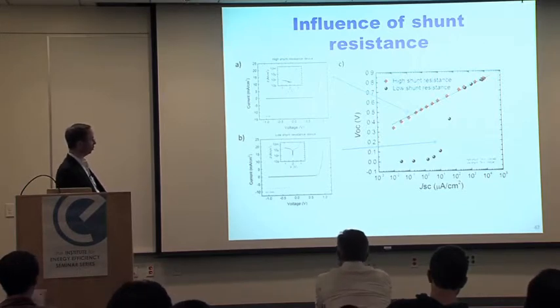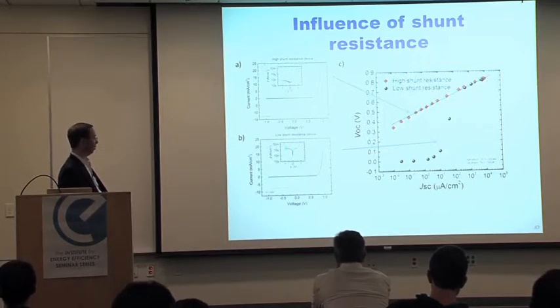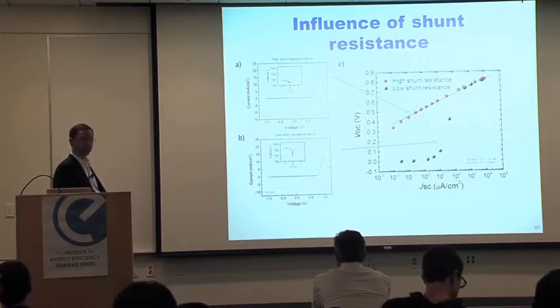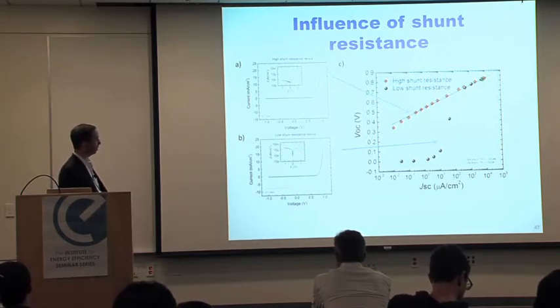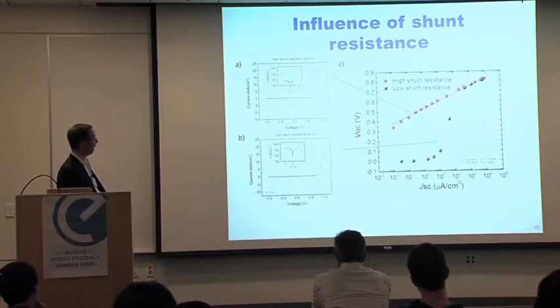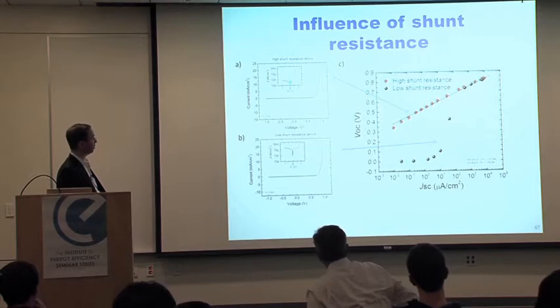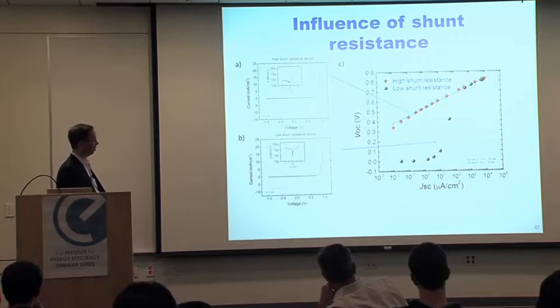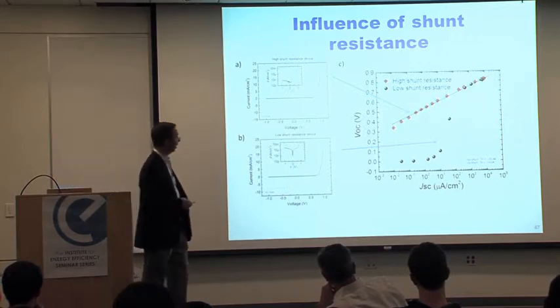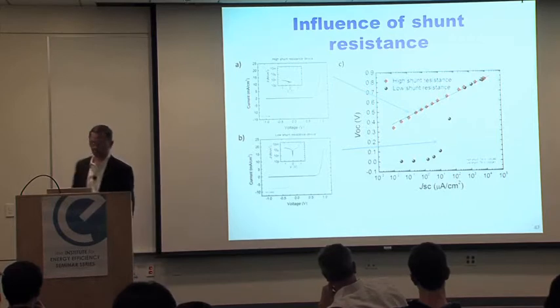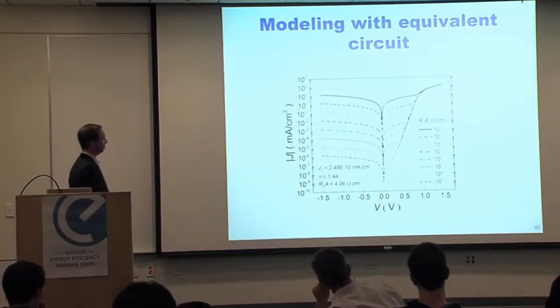And so the conclusion here is that if you measure a high current in the dark in reverse bias, which means that you have a low shunt resistance, because these devices most of the time are dominated by these parasitic effects, then you get that kind of behavior which is not typical for a diode. But if you have devices where the shunt resistance is large enough, and there you can actually vary the light level by 6 orders of magnitude, and it follows perfectly well the behavior of a diode. And this can be seen here.